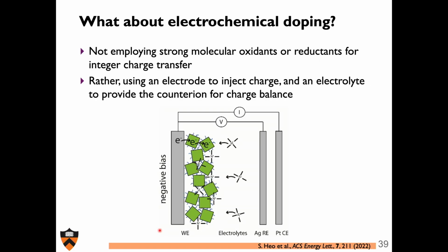So then we tried using cesium-lead bromide nanocrystals, to see if we could dope those through electrochemistry. The way this works is pretty simple. You put your cesium-lead bromide nanocrystals on a surface, in this case ITO. You immerse it in an electrolyte. In this case, I think it was TEA PF6, I can't remember the counter anion. But you inject electrons from the ITO electrode, and every time you inject an electron, you attach one of these bulky ammonium cations to the surface, and that's electrochemical doping.